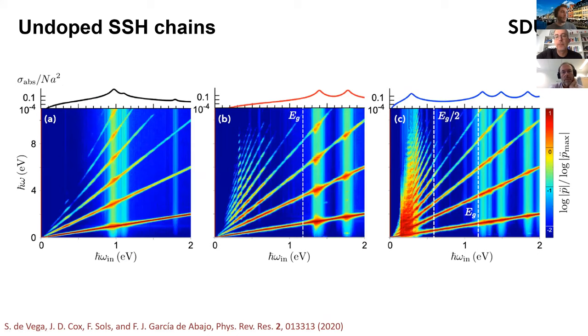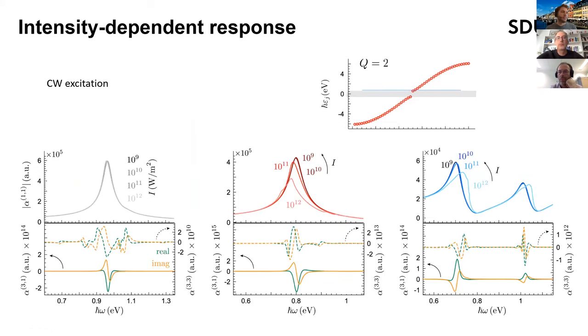Yeah, that's a great question. And they do, so it's again kind of a qualitative versus quantitative story. Obviously, if we choose a smaller phenomenological damping and we're talking about these plasmonic enhancement effects, they will become much more effective, right? But actually it can also lead to a quicker onset of saturable absorption. So in a way, like you see in this figure here with the CW simulations, you're shifting the plasmonic resonance or saturating it when you drive with really intense light. So if I have a lower damping, that field concentration gets even stronger and it can quickly saturate. Eventually, on the numerical side, the solver will fail at some point if we take an arbitrarily small damping and a very high intensity. So it kind of sets the threshold intensity for triggering the nonlinearity.